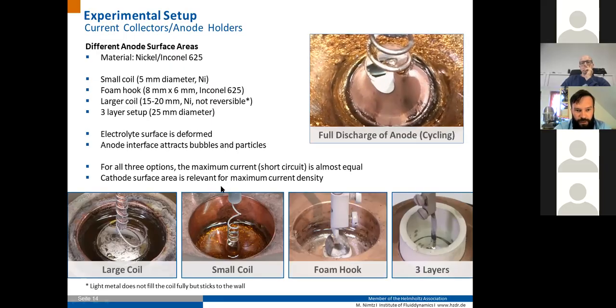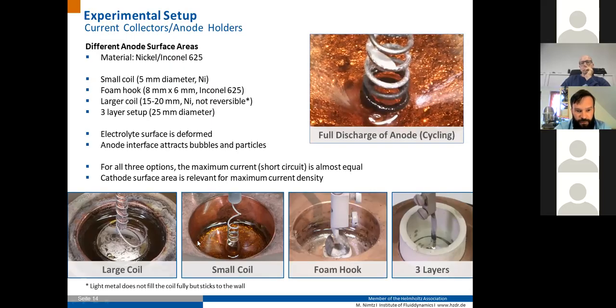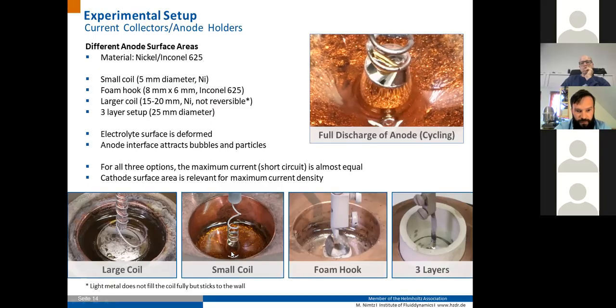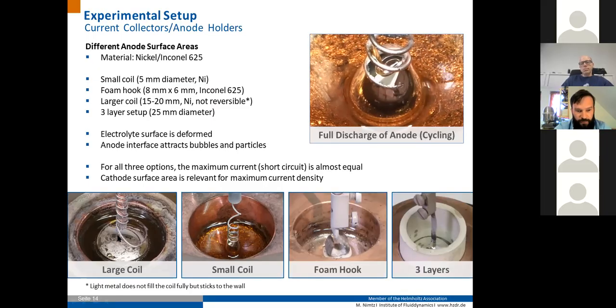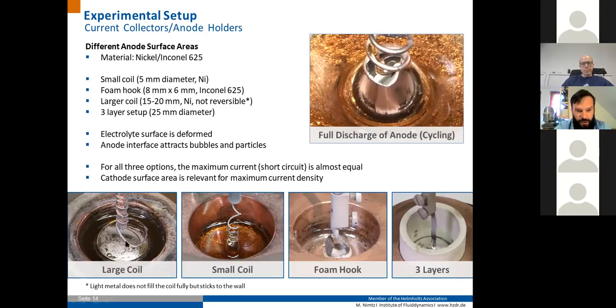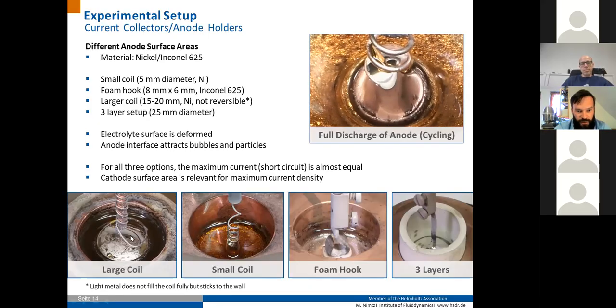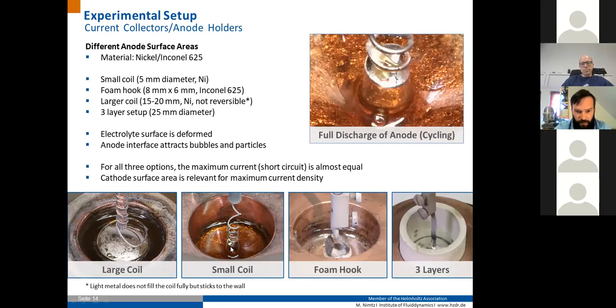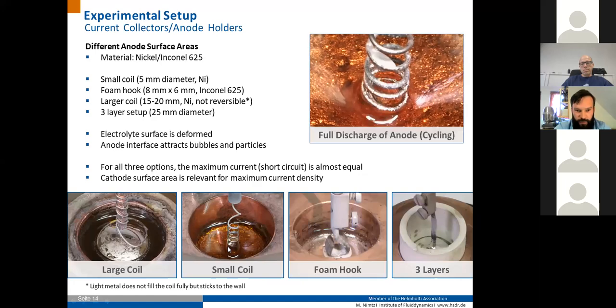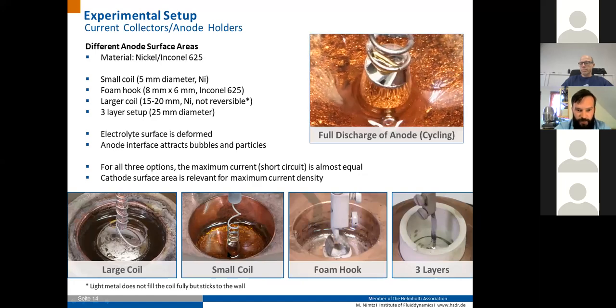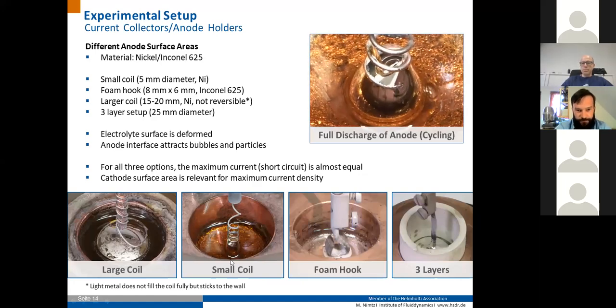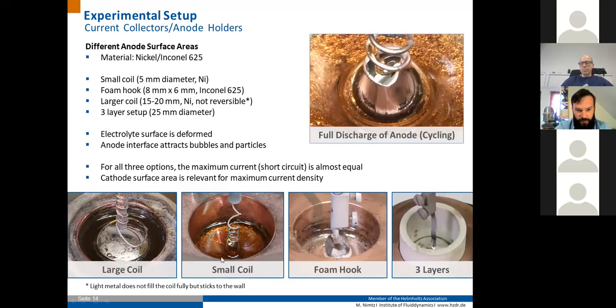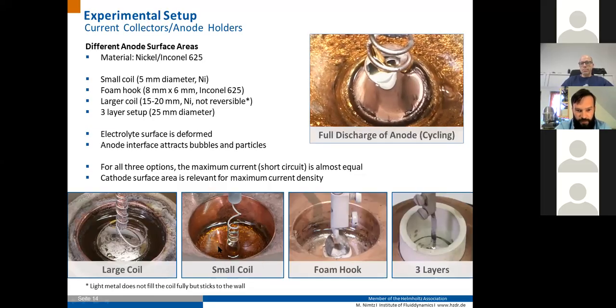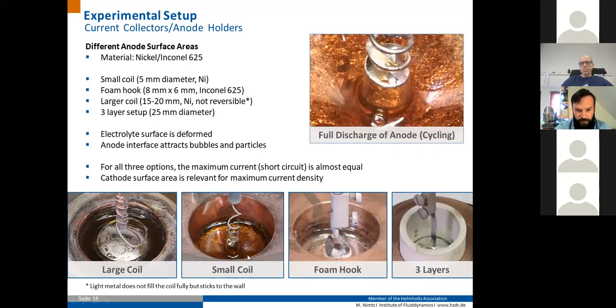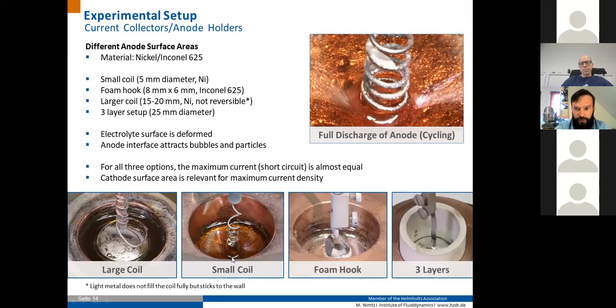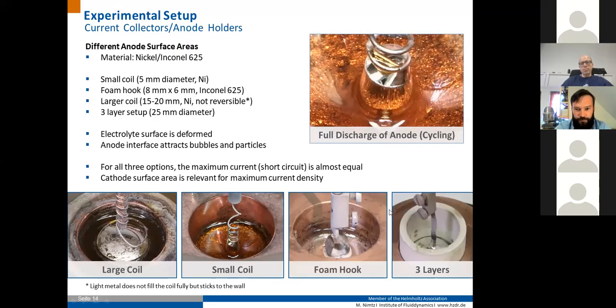And this makes it also hard to get real numbers for current densities occurring in these experiments. The difference in current you can get from these cells is quite small, even if we have such large diameter coils or such small lithium droplets. The maximum short circuit current is almost equal. And this leads to the conclusion that the cathode surface area is much more relevant for maximum current densities.